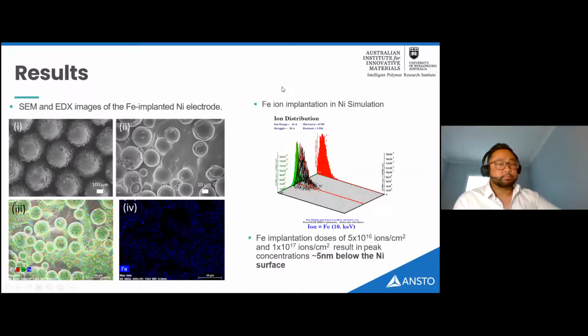Next slide, please. So this slide shows the SEM and EDX results. From SEM on the top left image, you can see the cones from above, and you can see the remnant spherical particles on the cone surface from the selective laser melting technique. What's important is the EDX image on the bottom right, which confirms that we could see iron after the iron implantation. On the right is the iron distribution curve, which shows that the depth of the iron implantation was about 5 nanometers from the surface, so within that 10 micron thick nickel film. Next slide, please.